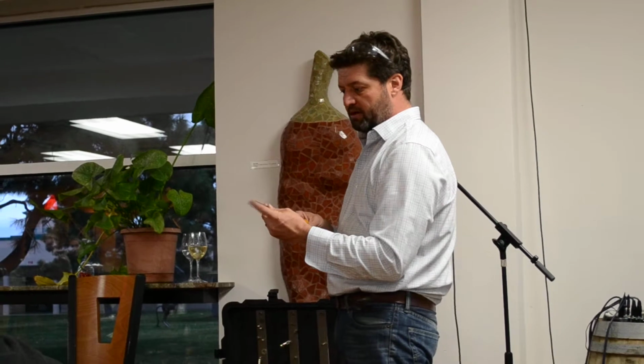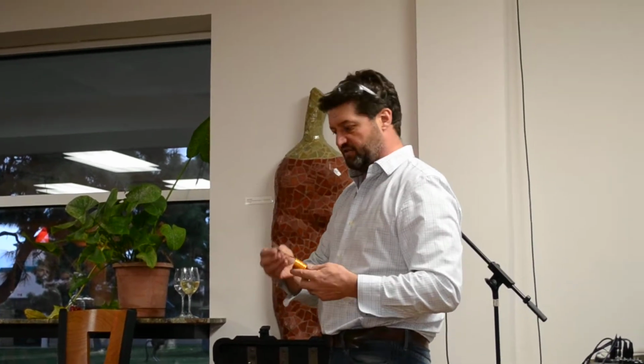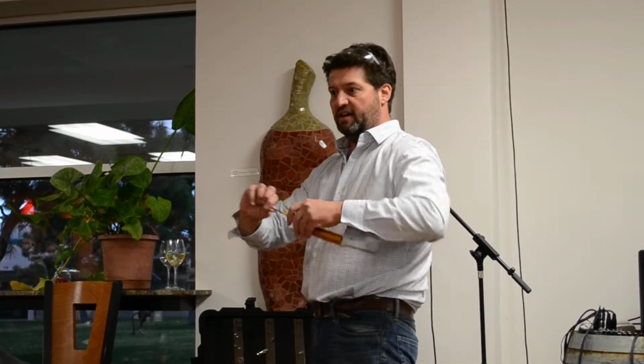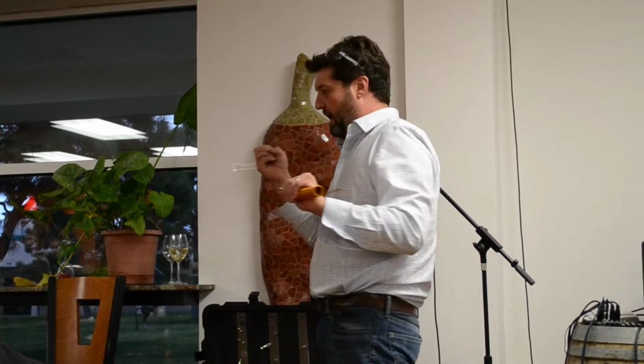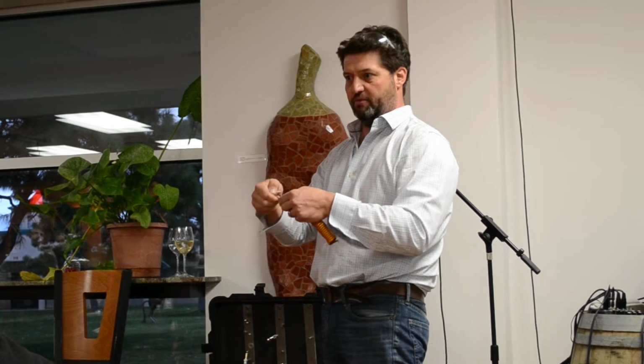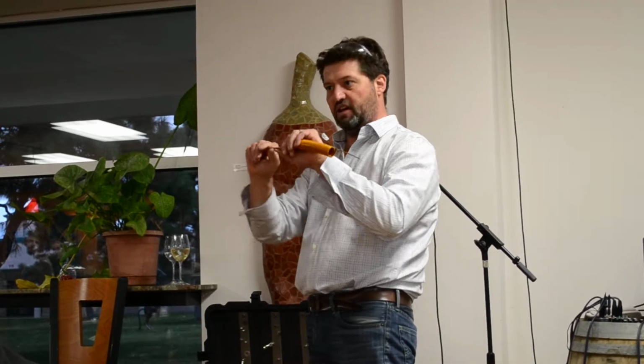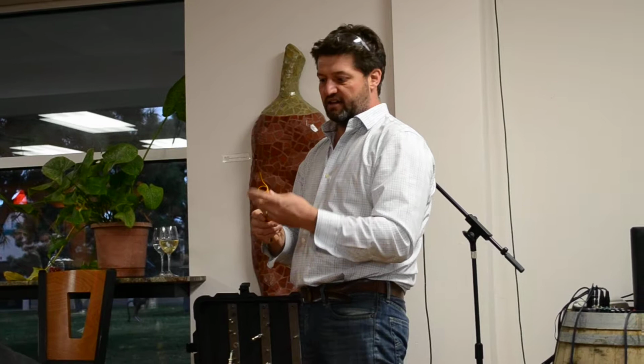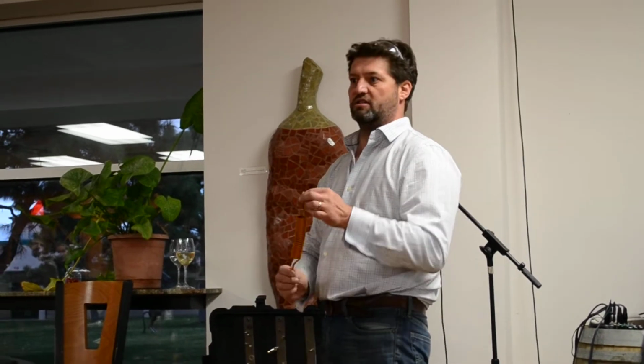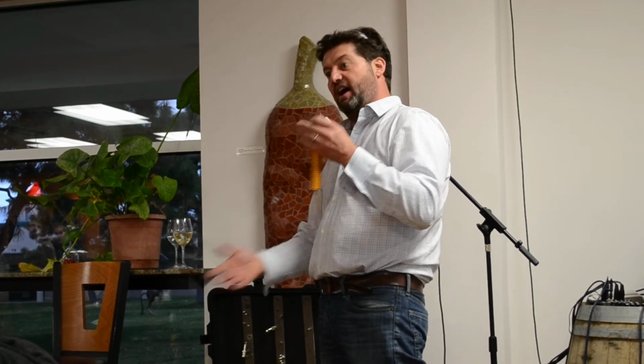This is mainly copper, but we have various alloys of copper. This is probably what we call Glidcop, which is copper with alumina powder in it, sapphire, aluminum oxide. And that basically, a bit like putting gravel in your cement to make concrete, makes it a tougher material, means that it's harder to have dislocations and bend it. There are other things you can do, a bit like putting rebar in there to make it stronger: copper niobium, copper silver. There are other alloys where you're trading off the conductivity, how fast it heats,